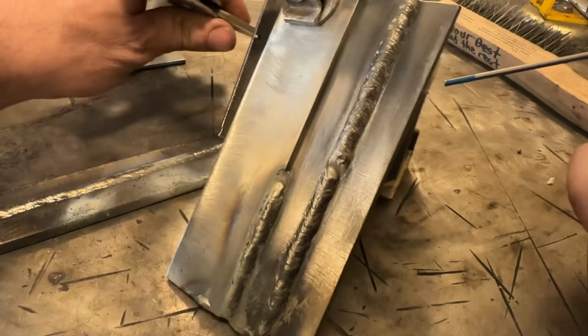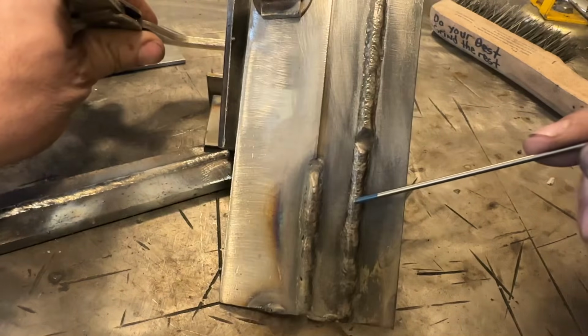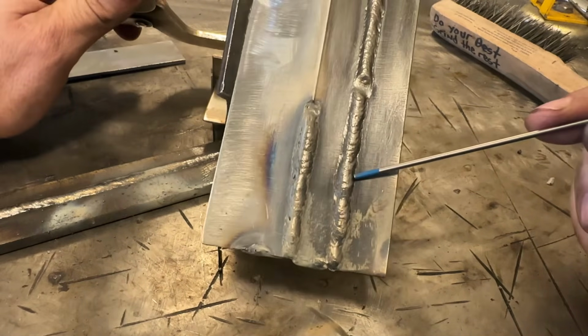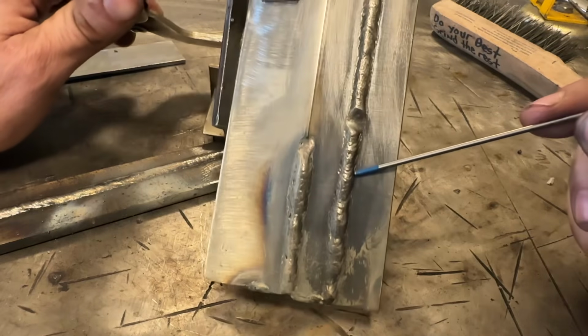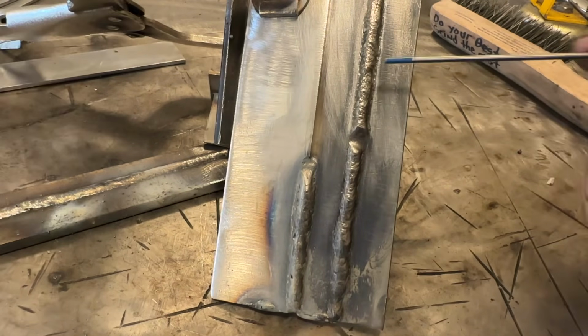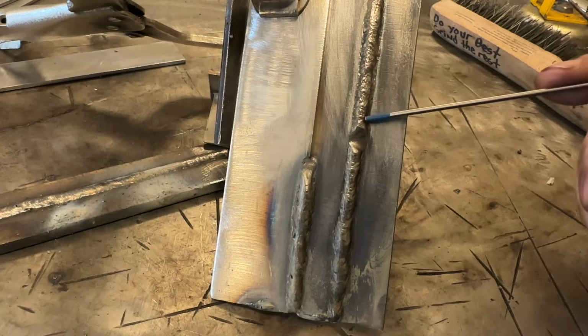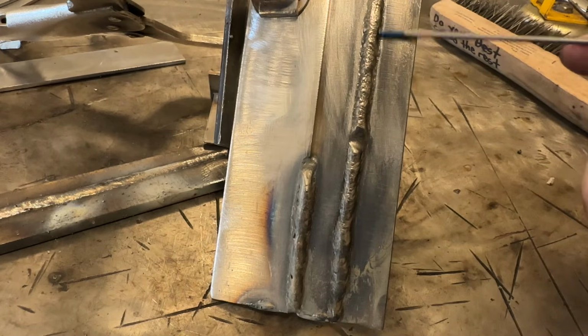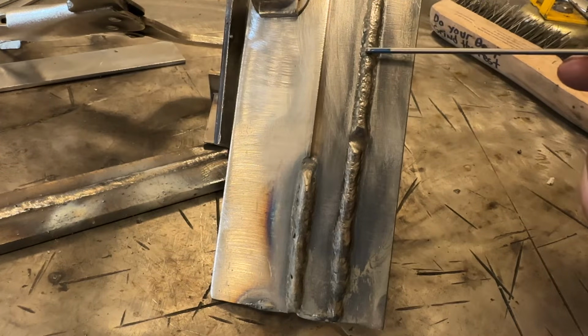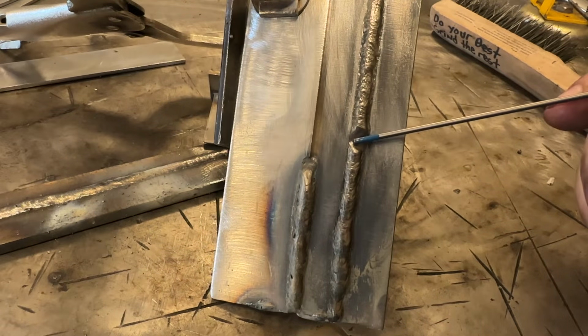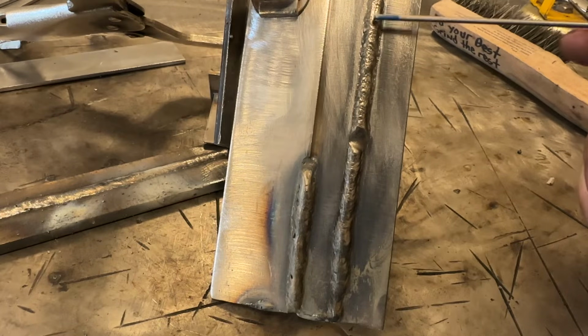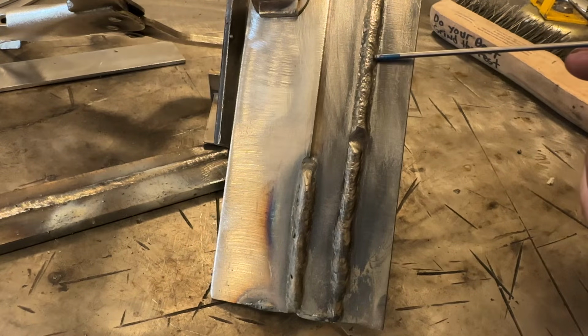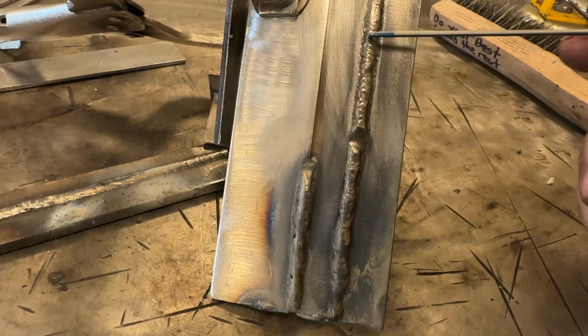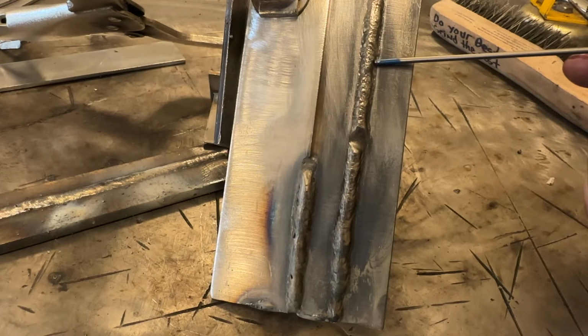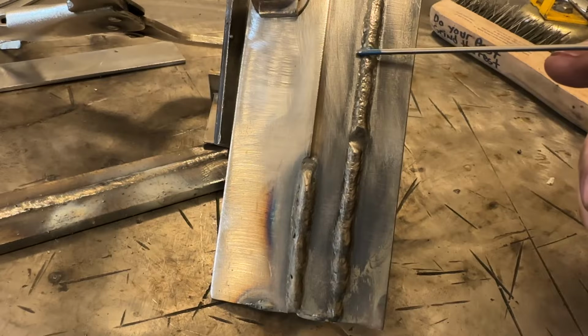Now I'm going to tip this just to show you. A lot of it's simply the lighting, and you can play with the lighting and it looks different, but out of all three of these so far, this is what you definitely want to be aiming for. Now I have a little bit of inconsistencies on the toe line here, which is very common welding vertical up. From a strength perspective for 1/8 inch, this is definitely strong enough, more than strong enough actually, because there will be penetration in the root of this, plus a slight cap that's a little bit above the base material.